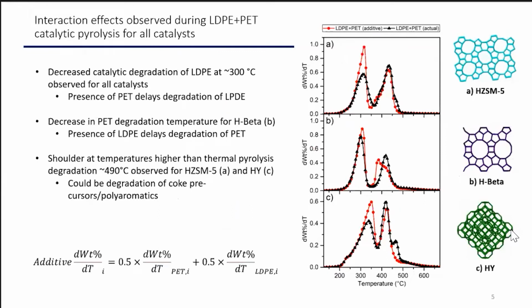So now that we have done the individual pyrolysis of these polymers, what we are able to do is calculate an additive curve. So this is the curve that we would expect to see during the co-pyrolysis. And this is the curve shown in red for these figures. Then we ran the actual co-pyrolysis at this 1:1 LDPE to PET ratio. And what we see is that the actual curve is not the same as this additive curve.